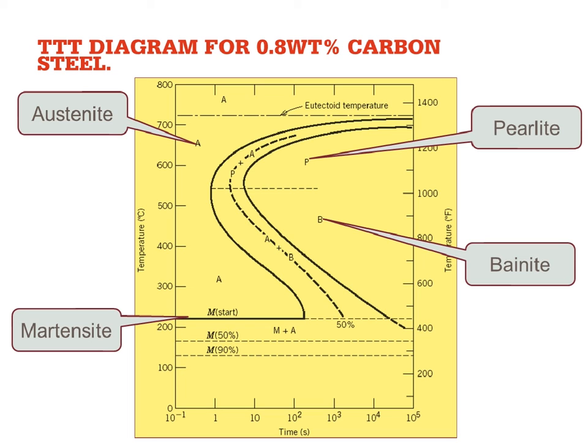And this is showing us the temperatures at which the different phases, the austenite, the martensite, the pearlite and the bainite, are formed. So if we start at the top left-hand corner at, say, 800 and cool slowly, so we get down to 600 degrees after, let's say, 1 hour, 3,600 seconds, that would produce pearlite. If, though, we started at 800 and we cooled down to 200 degrees C in, say, 2 or 3 seconds, that would produce martensite. So it's these diagrams that are used as a roadmap for the heat treatment of steel.